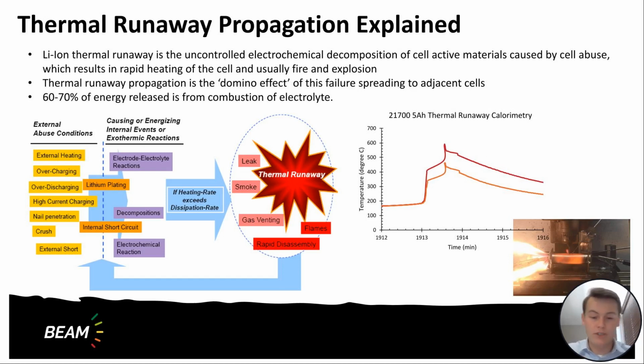The result of those occurrences is you start to have reactions inside the cell between different active materials such as electrolyte and cathode or anode materials. That's an exothermic reaction, so the cell heats up to a point where, if the heat released from the cell doesn't match that, you obviously get continual heating to a point where the separator melts. The separator chemistry varies, but 150 to 170 degrees is sort of the ballpark temperature where the separator melts. At that point, you have internal short circuiting throughout the cell and really massive current dumping throughout the cell,